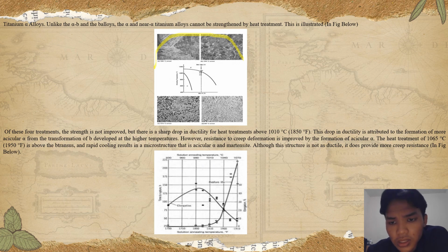1010°C (1850°F). This drop in ductility is attributed to the formation of more alpha from the transformation of beta developed in the higher temperatures. However, resistance to creep deformation is improved by the formation of acicular alpha. The heat treatment at 1065°C (1950°F) above the beta transus, and rapid cooling, results in a microstructure that has acicular alpha and martensite. Although this structure is not ductile, it does provide more creep resistance in the picture below.